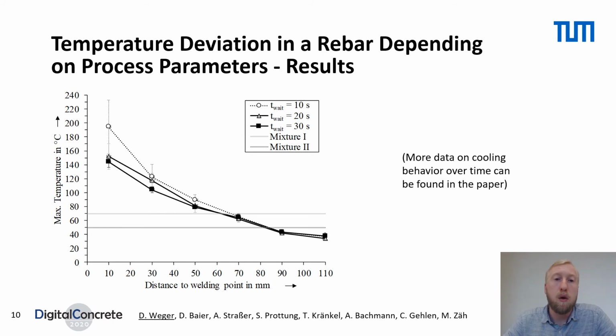Close to the welding point, the waiting time has a great effect on the temperatures. However, the further away the measurement point is from the welding point, the lower is the effect of the waiting time. From a distance of 70 mm, the waiting time is no longer decisive.